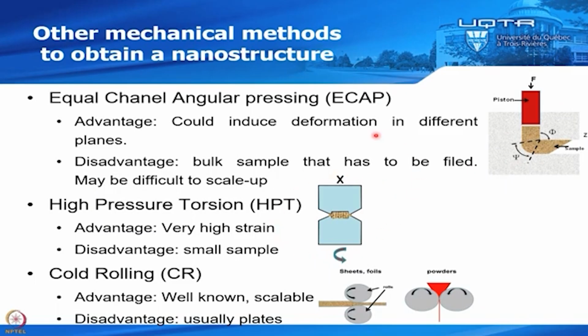The other technique that is more and more used now is high pressure torsion. So here your sample is a thin disc that you put between two anvil, and you rotate it. You rotate the anvil and you press on it very hard. So the advantage is you have a very high strain. Maybe this is the technique that you have the highest strain. But the disadvantage is you have a very small sample. So maybe it's 1 centimeter of diameter by maybe 1 millimeter of thickness. So your sample is very, very small.